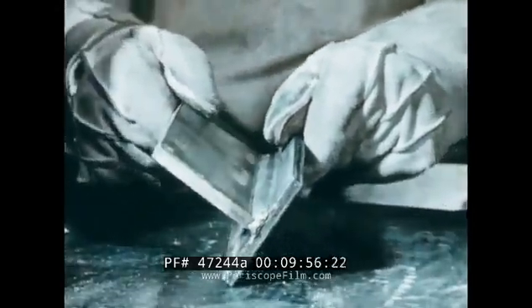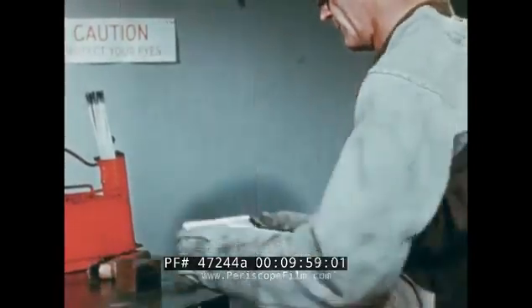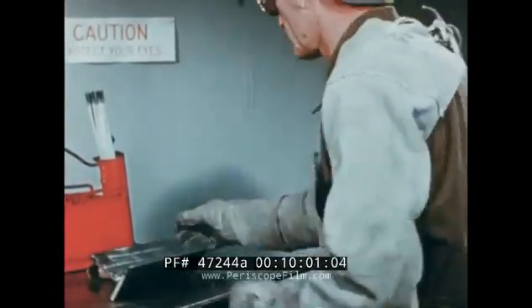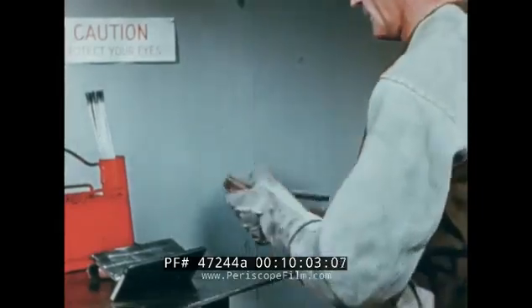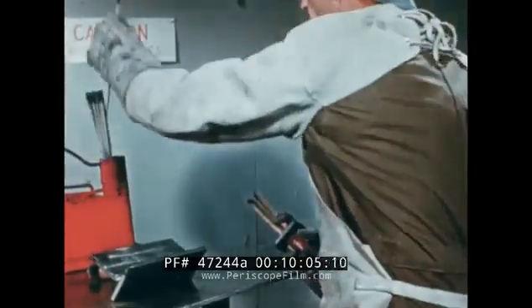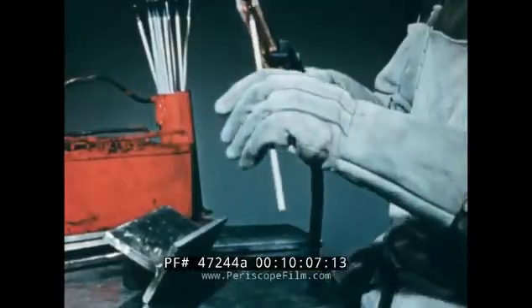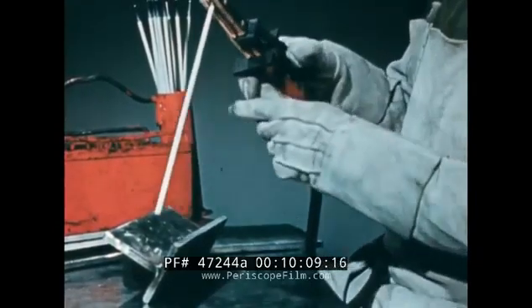Both the size of the electrode and the thickness of the plate to be welded must be considered in making the proper current setting. Here we're using a 3/16 inch diameter all-position electrode, AWS class E6010 with direct current reverse polarity. So with a normal arc, we should have a machine setting of 130 amperes. This will provide us with 26 to 28 volts.